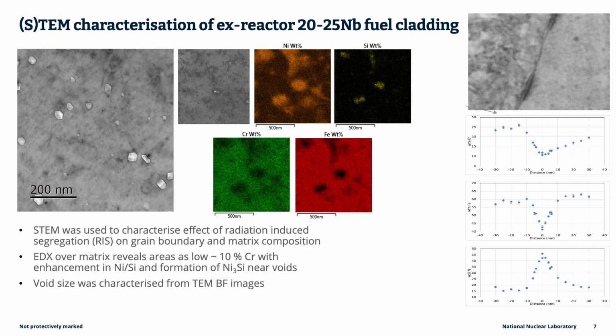electrolytically. And that did cause us quite a lot of problems when we were trying to examine grain boundaries in this material just before the FIB arrived, and we found the grain boundaries were etched away and we weren't seeing any chromium depletion because it had all been polished out by the electropolishing.